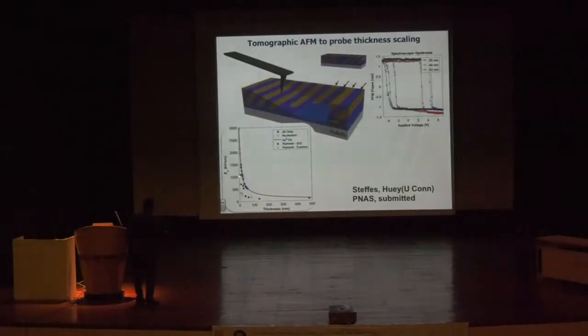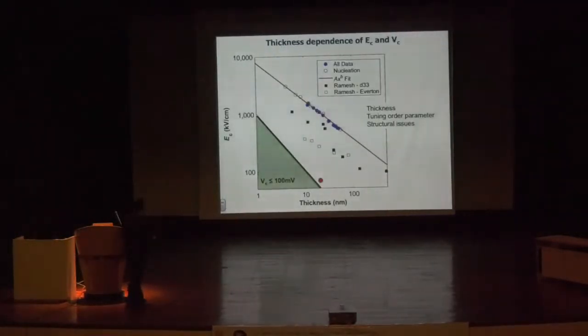And indeed, the coercive field for the same sample looks like this. Let me show it to you in a slightly different way. This is plotting the coercive field versus thickness, and you can see that's the data. It does indeed go as minus 2/3, so it is very well fitting to the prior data. But you could also see that these are AFM-based measurements. These are measurements of the same bismuth iron oxide composition, but by using a capacitor structure, which means my contact electrodes are very important. And therefore, interfaces play a big role in how the switching happens.